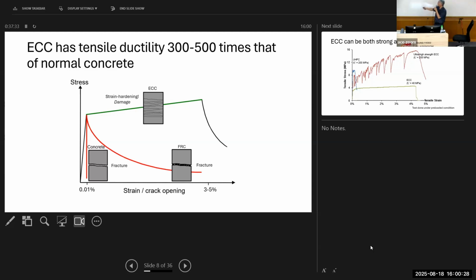What we are looking for is this behavior in green. We have a strain hardening behavior. Even though the material is damaged, the load carrying capacity continues to rise. And how far, how much? Well, a good way to measure is this number, tensile ductility. When does this branch begin to descend? And in this example here, for ECC, it typically goes from 3 to 5% tensile strain.